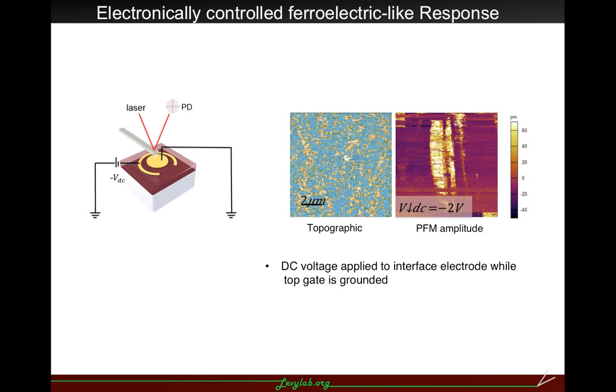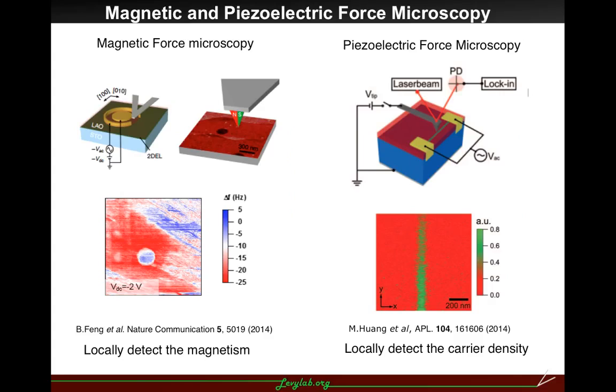Since the top gate and interface electrode can effectively tune the carrier density at the interface, we performed this piezo force microscopy on top of our LAO-STO heterostructure. The PFM amplitude channel shows a significant contrast when a negative voltage is applied to the interface electrode. This is very similar to what we saw in MFM.